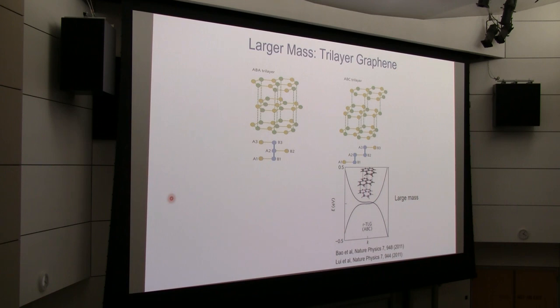For each monolayer graphene, you have a hexagonal lattice. You have A and B, two atoms in a unit cell. And in ABC stacking, these atoms form a stair-like structure. In this case, some of the atoms sit directly above and below each other, so they strongly hybridize and form bonding and anti-bonding states. So they are pushed away to high energy. At low energy, we are left with a top B atom and a bottom A atom. They have the same energy, so you actually have a zero gap. They couple very weakly with each other because it needs to go through many steps. So it has a small dispersion, which means a relatively large effective mass.